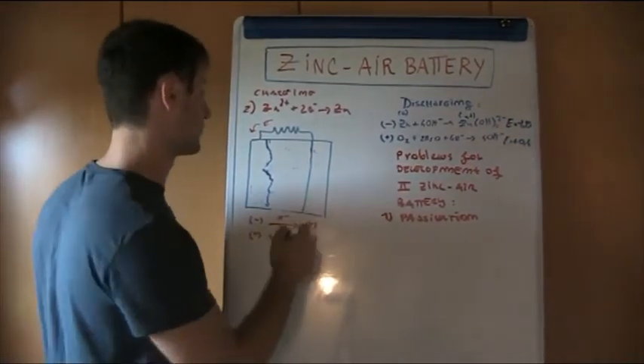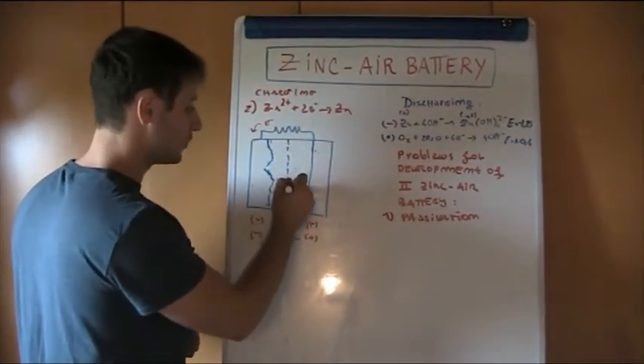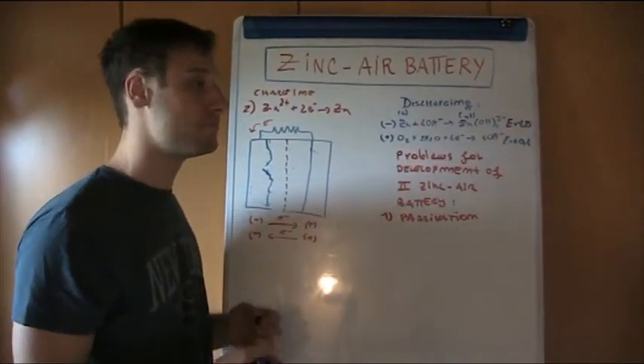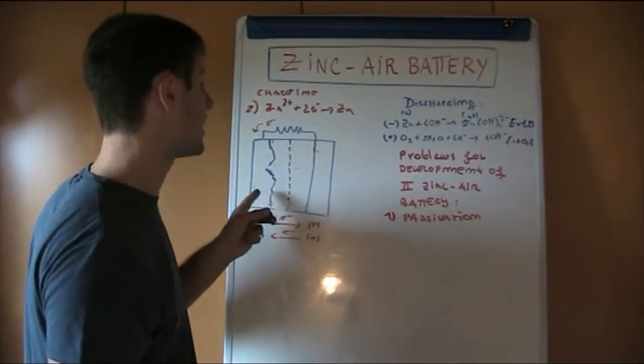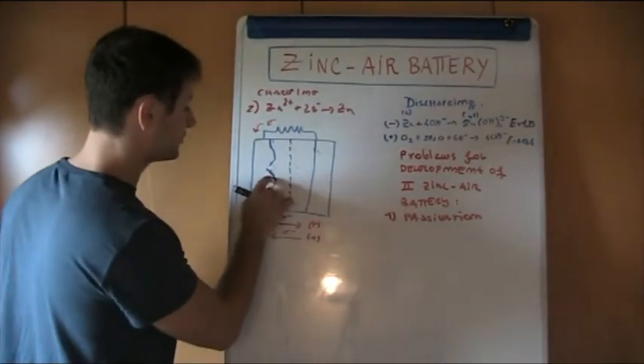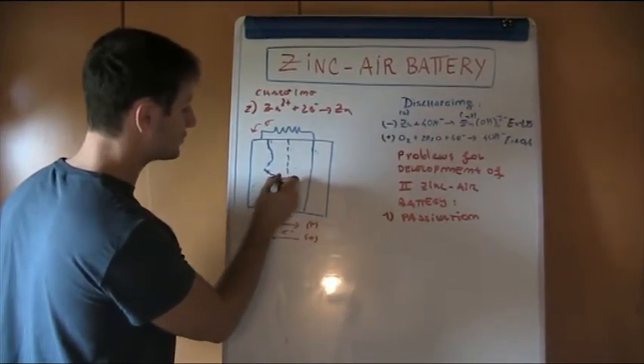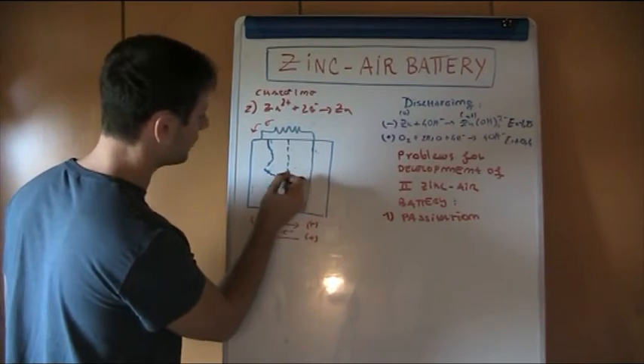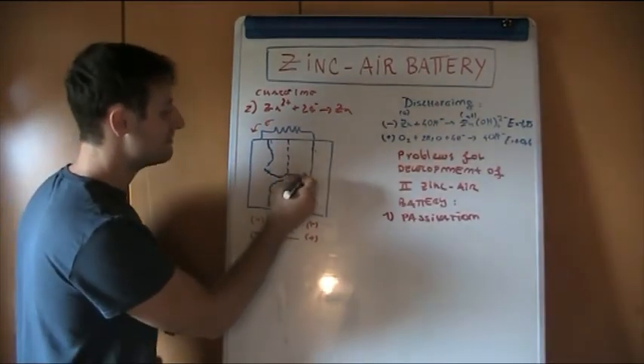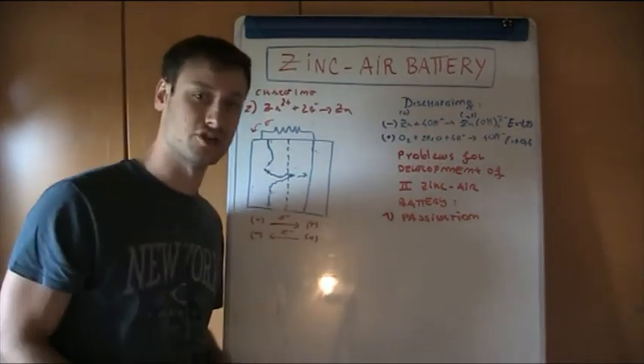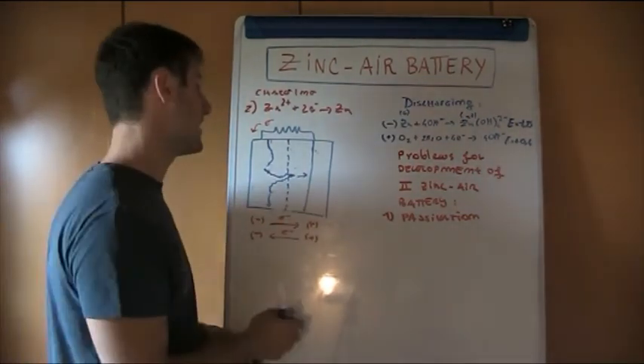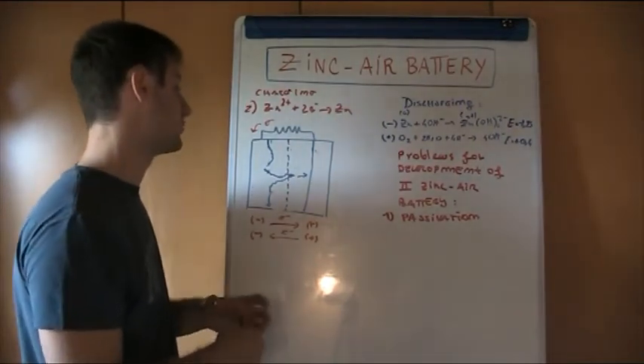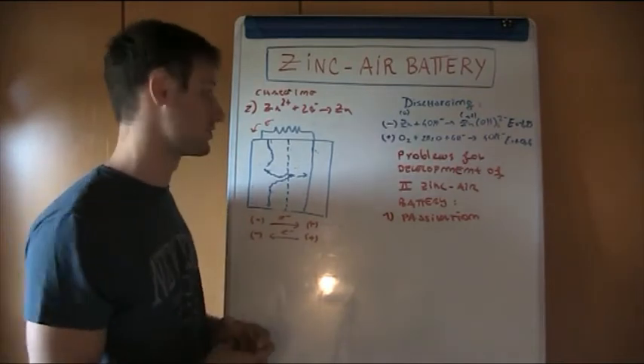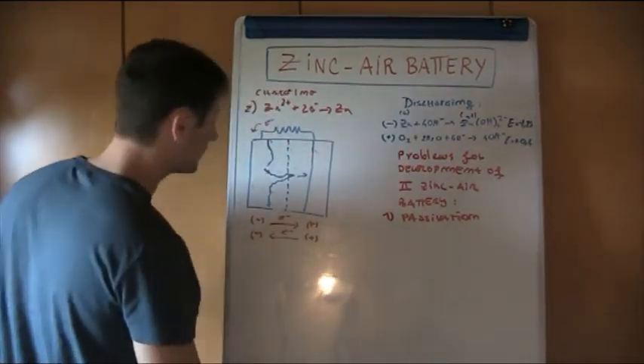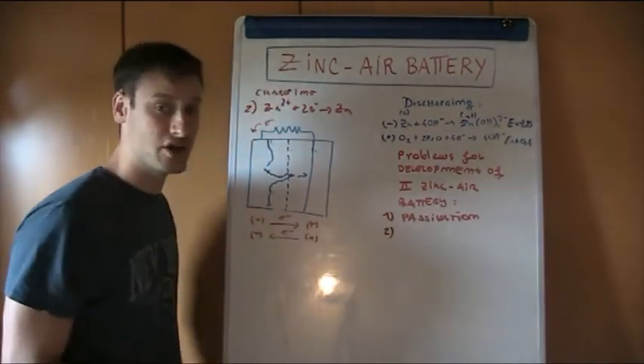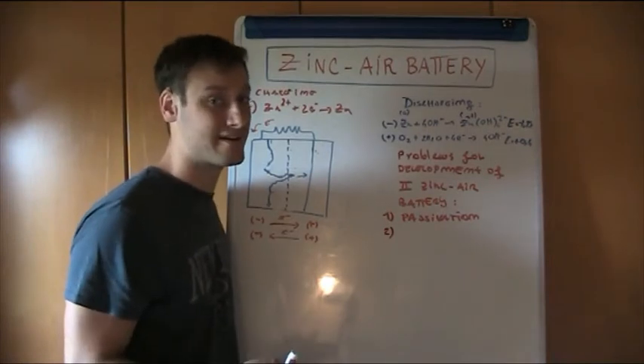And another extremely important process is that, remembering that we have a membrane, an ionic permeable, electronic impermeable membrane in order to close the circuit, avoiding the contact between the electrodes, if the redeposition mechanism is so bad and so localized in one point in order to create something that can break down this membrane and even maybe reach the other electrode, we can cause a short-circuit and make the system explode. And so basically this is a real problem, this is a real hazard also. So the second problem lies in bad redeposition mechanisms with the formation of aggregates and changing the morphology.